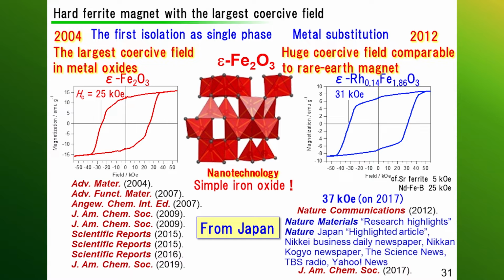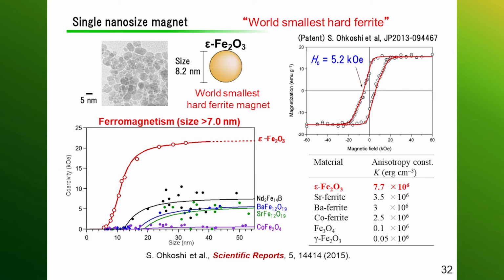Material with such outstanding property also has diverse functions, and one example would be a capability to maintain magnetic property even when the size is smaller. As you know, magnets can be reduced down eventually to a single atom, but it is no longer a magnet. But if a material has a high level of coercivity, it may be maintained in smaller size. For example, we achieved coercivity in a particle as small as 8 nanometers while maintaining 5.2 kilo-Ørsted.